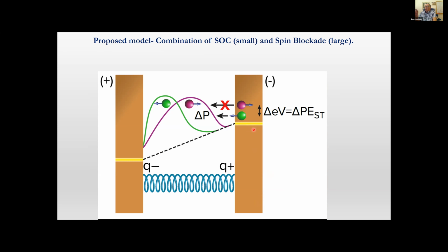the molecule. The first thing that happens when a field is applied on the molecule is charge polarization due to its polarizability. Now, because chiral molecules have an anisotropic polarizability, it means that the polarizability is spin dependent. I don't want to go into it in detail, but the polarizability is spin dependent. As a result, we get, if you wish, momentarily, two types of charge distribution, one for one spin and one for the opposite spin.